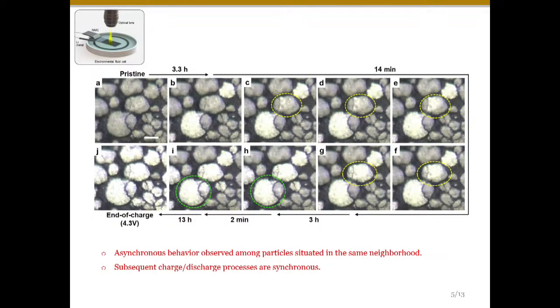Another important thing with the result was, if you look at the zoomed-in picture, the particles which are in the near neighborhood don't simultaneously change their intensity. Since there is ample electrolyte here and we are looking at the particle surface which is equidistant from the current collector, we tend to believe that this is because of the carbon network which goes to the current collector from this particle.